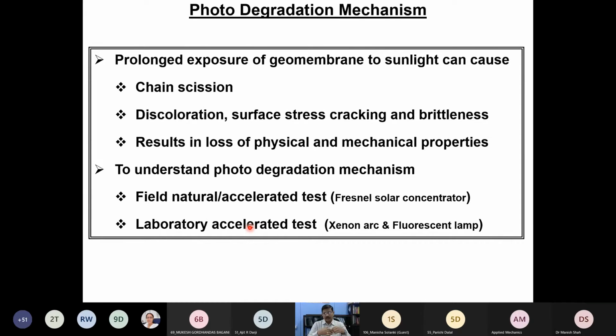As a result, the polymer will lose its physical and mechanical properties when subjected to photodegradation. In order to understand these mechanisms, people have conducted both field studies as well as laboratory studies. Please note that with exposure of a polymer in the field, you may have to wait a prolonged period of time to see a noticeable change in material property. As a result, in the field people also accelerated the method by using Fresnel solar concentrators, where the wavelength is not changed but the intensity is increased. But even the accelerated and natural testing methodology demands a substantial amount of time, like 10 to 15 years, to completely degrade the polymer.